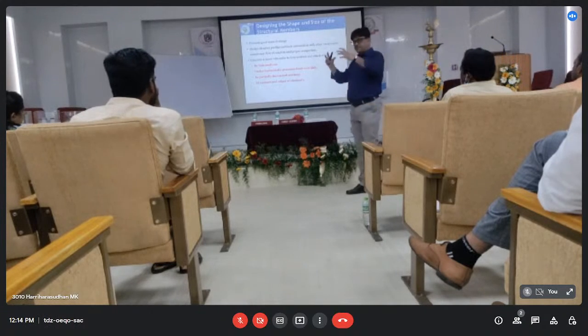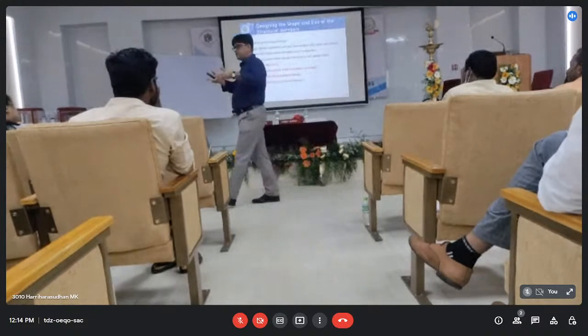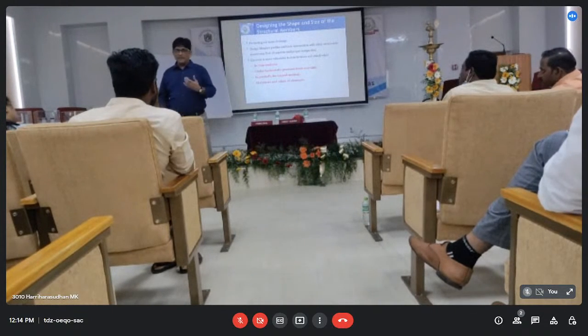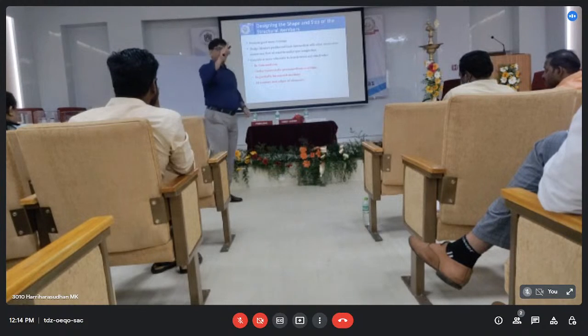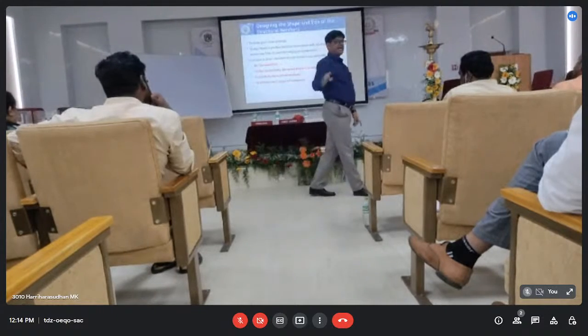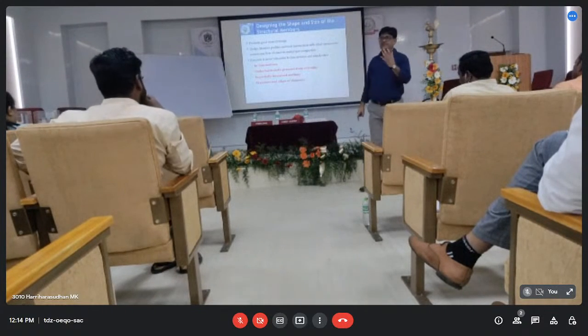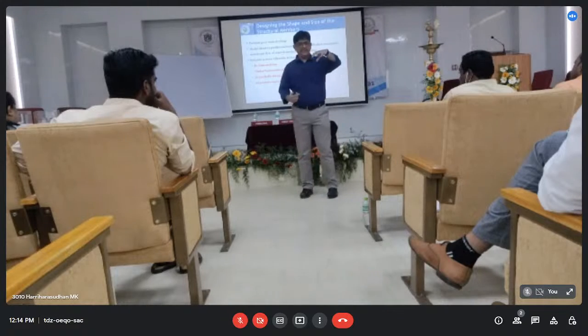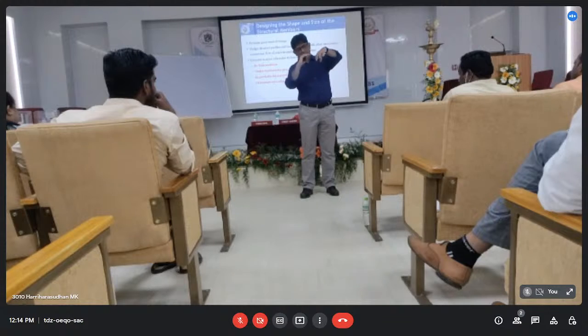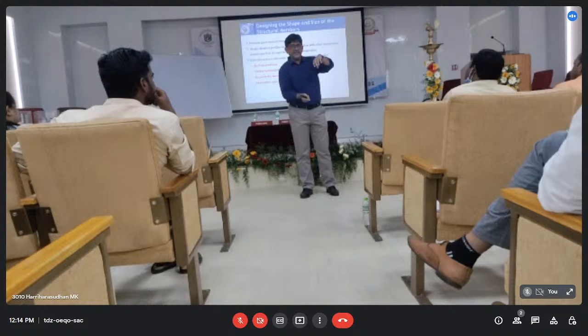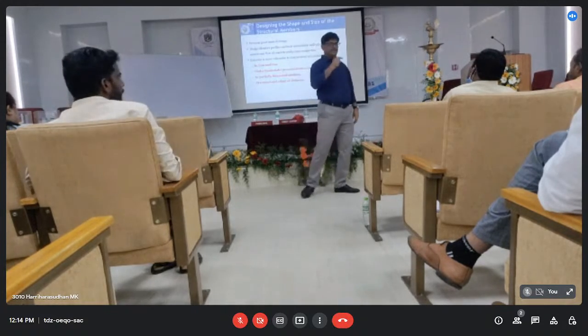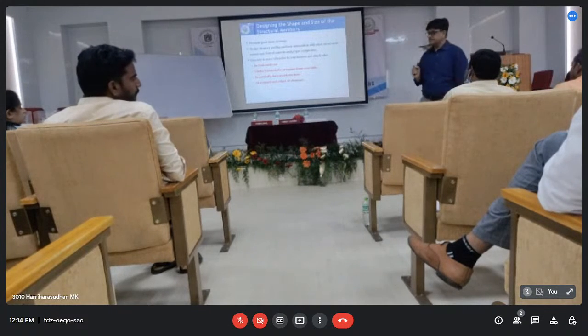The columns, my substructures, my foundation, which are in partially immersed sections. Some bits of the areas are in contact with water, some bits of the areas are outside. So there is a continuous wet-dry cycle which happens on that structure. You might have seen on river bridges, the columns of the piers, where the water touches, the up and down portion, that much section gets maximum damage. Because there is a continuous wet-dry cycle. The water goes up, goes down, goes up, goes down. Continuous. So that is a section which is very, very critical.